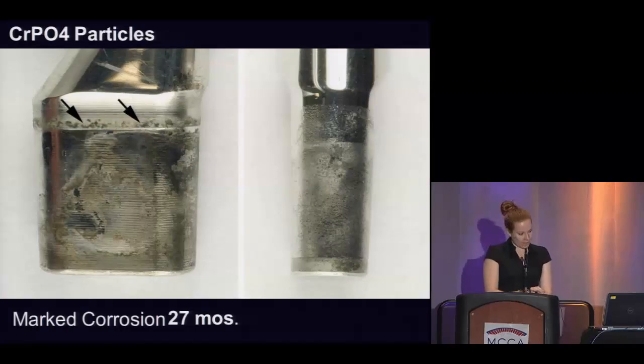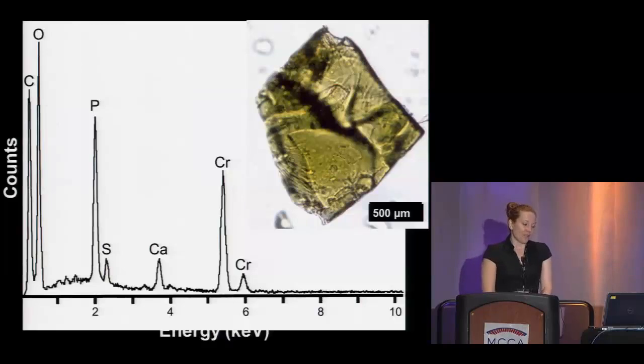Another characteristic of the periprosthetic tissues was the presence of chromium phosphate corrosion particles. Here, the arrows are indicating the appearance of these chromium phosphate corrosion products on the opening of the modular neck device where it adapts at the stem. These corrosion products appear translucent, pale green, amorphous, and non-birefringent, and are often very brittle, breaking off in many small pieces.